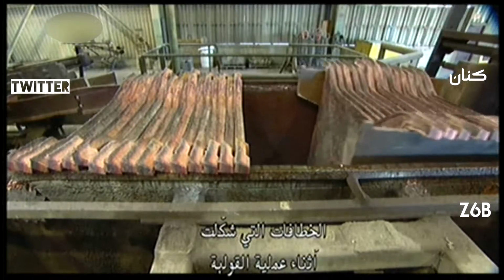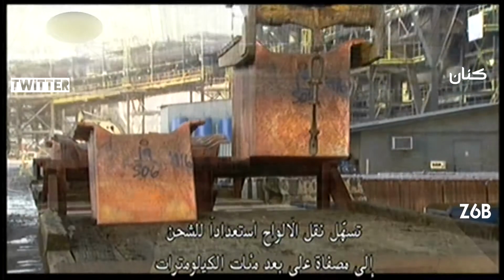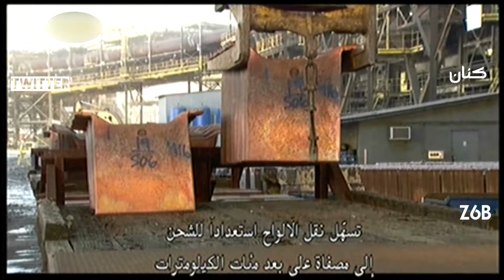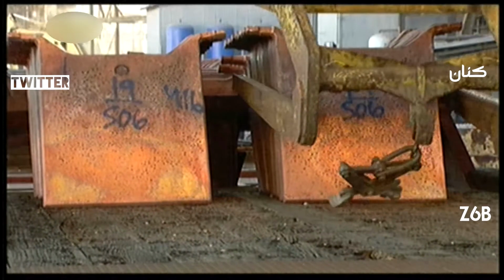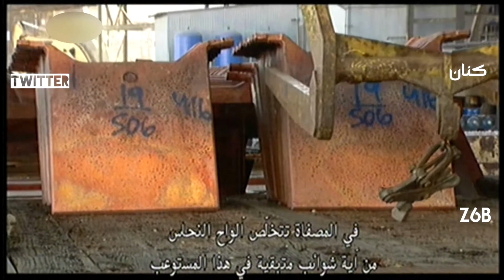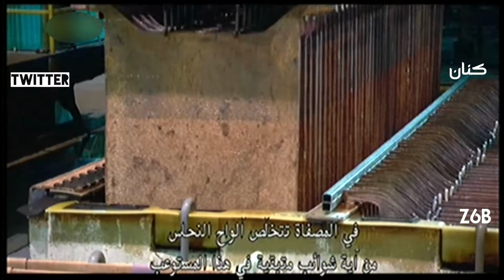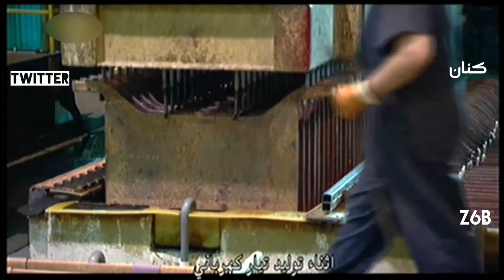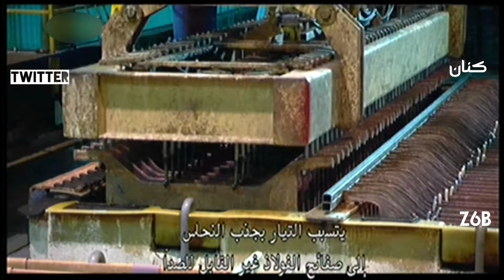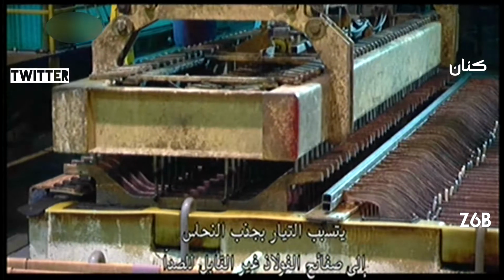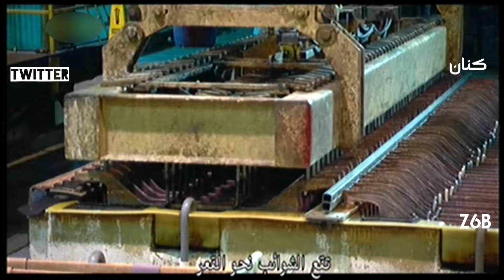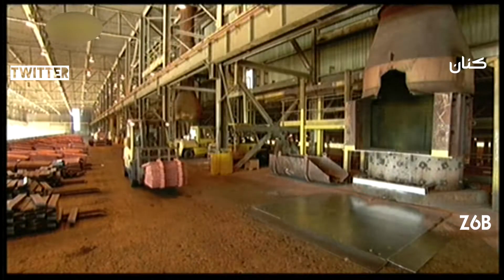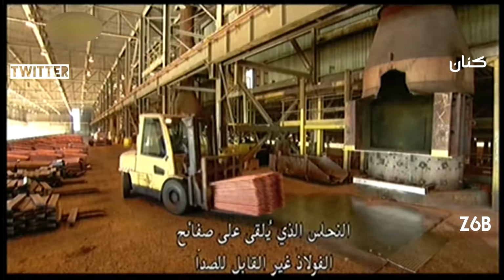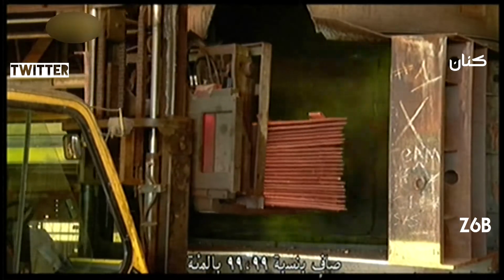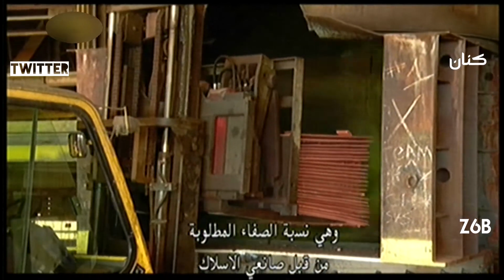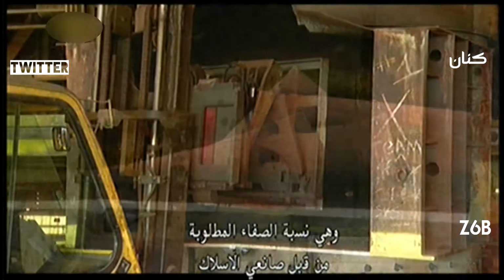Hooks formed during the moulding make it easy to rack up the slabs for shipment to a refinery hundreds of kilometres away. At the refinery, the copper slabs shed any lingering impurities in this tank as an electrical current is applied. The current causes the copper to gravitate to thinner starter sheets. The impurities fall to the bottom. The copper deposited on the starter sheets is 99.99% pure, the purity level required by wire manufacturers.